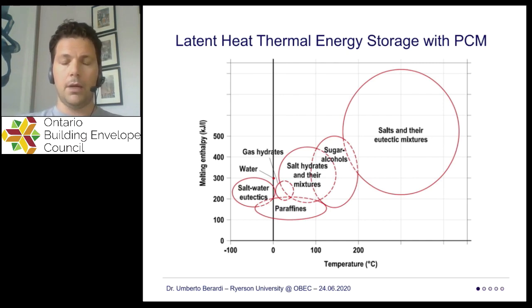Here you see a graph where you have the temperature at the bottom and the melting enthalpy on the vertical axis. So the y-axis tells you how much energy you can store in this material. And clearly, typically, the more the better, because if you have a higher melting enthalpy, a higher storage capacity, then you don't need to use a lot of phase change material. So typically, as soon as we can use materials with a melting enthalpy of 400, 500, 600, 700 kilojoules, it's good. But unfortunately, not a lot of products offer that property.